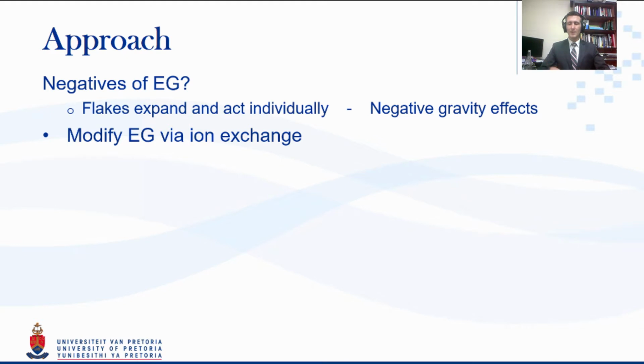So one of the first avenues of research we took was to attempt to modify this expandable graphite through ion exchange. That had a two-pronged reason. One reason was that by attempting to wash and ion exchange, we can get an indication of how loosely or solidly bonded the sulfate ions on the inside of expandable graphite are, and we could potentially put other ions in.